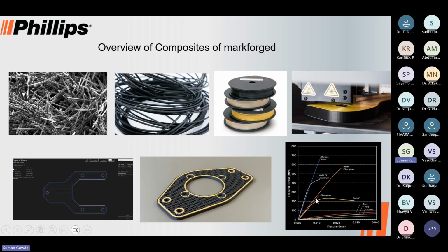And just to show you a comparison, for regular plastics we are looking at below 100, whereas when we combine it with this kind of fibers, we talk about strength of 200 and even up to 500. So there's a huge deviation whenever we have started to use the fiber. Now if you are using a fiber of, let's say, Kevlar, you know the kind of elongation that you can get. You can cross verify at what particular settings I'm going to get this kind of elongation. Obviously, it will not be true for all the settings. So you can make that particular comparison, and then it becomes its own topic. These are the kind of things that we are working out with a lot of institutes.